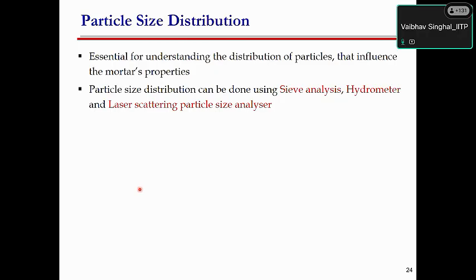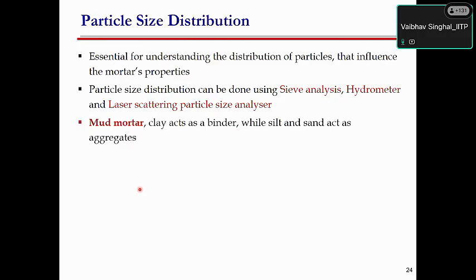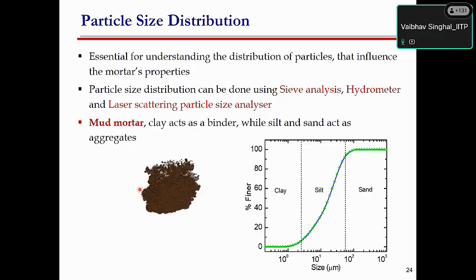We also did a particle size distribution, because to recreate the mortar, you should know the particle size distribution of the aggregates. So we did it using a hydrometer or using some advanced equipment like a laser scattering particle size analyzer. Interestingly, another thing we found is that for the bed joint in those times they were primarily using mud mortar. So this is a sample of mud mortar which has been taken from that site, and this is how the particle size distribution of this mud mortar looks like. So primarily consisting of silt and some part clay and sand.